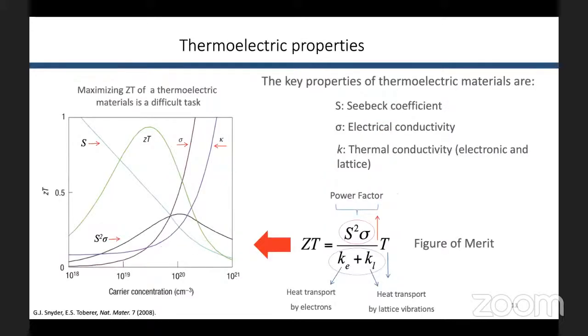Interesting is to analyze the thermoelectric properties, where the key is the figure of merit, this ZT, and that is the combination of three key properties. One is the Seebeck coefficient, another property is electrical conductivity, and the last is thermal conductivity. This figure of merit is the primary measure of material performance. And of course, enhancing this ZT requires optimizing the adversely interdependent properties, that is electrical conductivity or resistivity, Seebeck coefficient, and thermal conductivity. In this case, thermal conductivity, we can split into two: one related with heat transfer by electronic thermal conductivity, and another one related with lattice vibration by phonons that permit the heat transport.